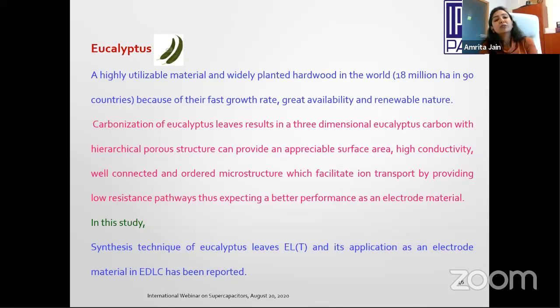You can find an ample number of eucalyptus trees. So it is a very highly utilizable material, the most widely planted hardwood in the world, almost 18 million hectares in 90 countries, because of their fast growth rate, great availability, and renewable nature. Carbonization of these leaves results in a 3D eucalyptus carbon with a hierarchical porous structure, which can provide an appreciably high surface area, very good conductivity, and good connected and ordered microstructure pores, which facilitate ion transport easily.